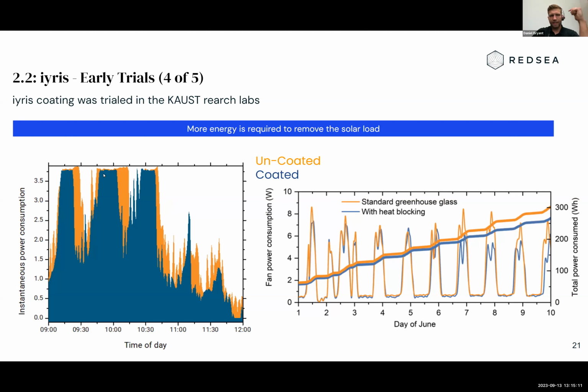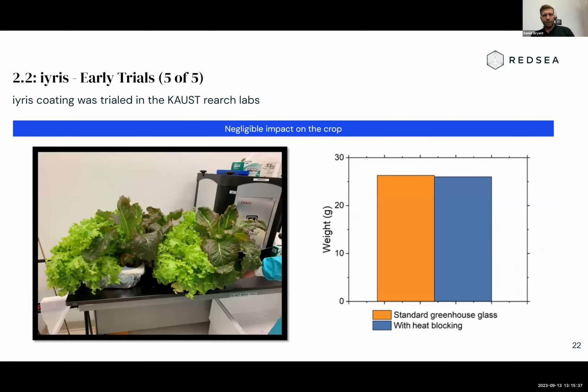What we saw was that you can keep the peak temperature the same, but when the sun starts to go, in the uncoated greenhouse the fans stay on, and so you consume more energy. Over time you have this widening of energy, and we found about a 25% energy difference even at this rough and ready early prototype stage. And again, this was enough to take this forward. Of course, the sample size of 2 times 4 lettuce was not exactly the most scientific we've ever done, but the fact we weren't seeing huge differences was enough to take this forward.